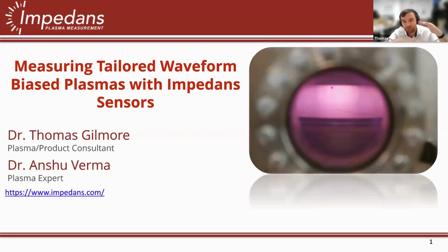Now in our chambers, which have a very massive distance between the CCPs, it's a completely negligible thing. If you have maybe a 20 millimeter gap or something between 2 electrodes, it is more significantly changing the geometry, which may change the plasma potential a little bit. So one thing to note is the distance change, but in general, it's negligible. In the majority of tools, it's a negligible change.